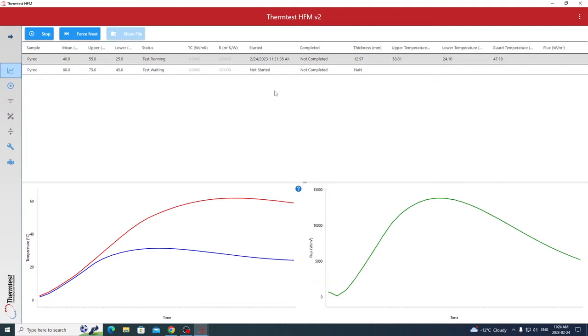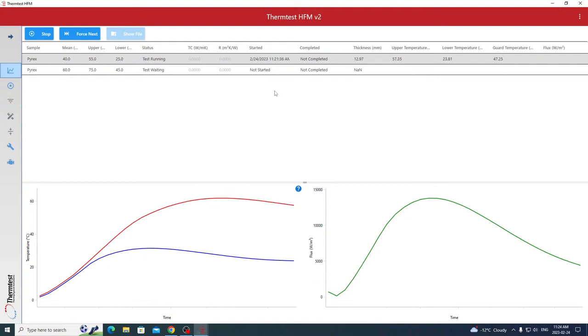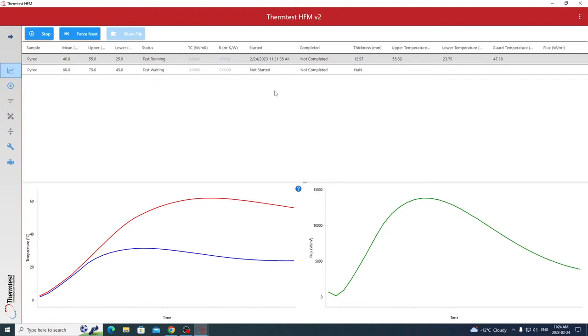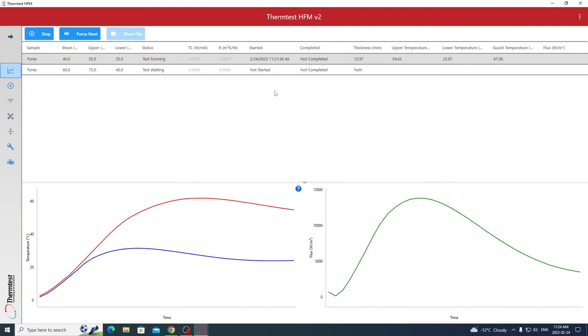So, when you're considering which method to use, if your samples are heterogeneous or not repeating layers or disorganized, the time thing should be second to the true value or accuracy, especially if you're using these values for thermal simulations, where you want the value to be high confidence, or even in specification sheets, etc., that you're using the true value. And that's why this method has been around for 30 years. This method is high confidence for measuring such materials.